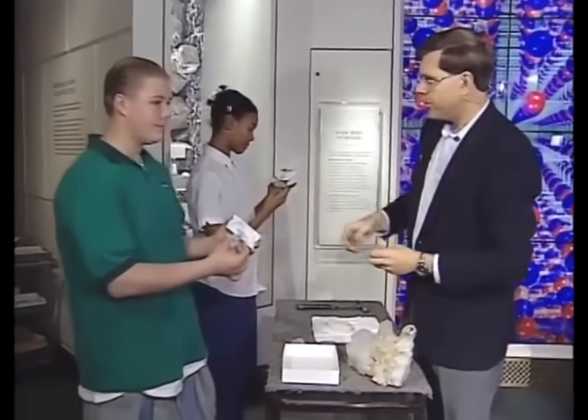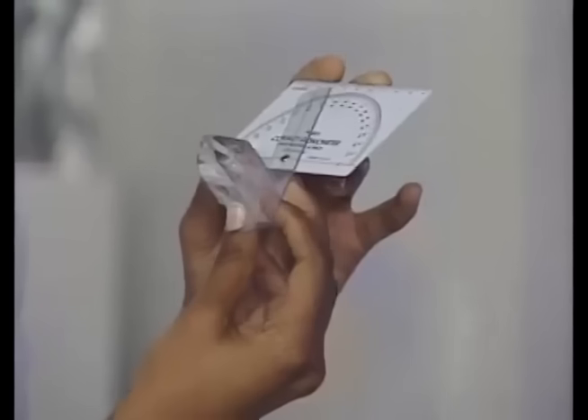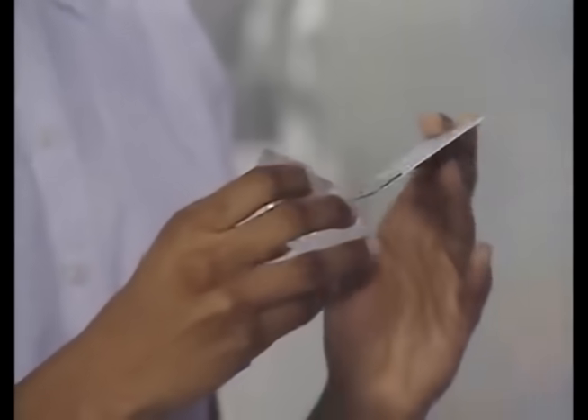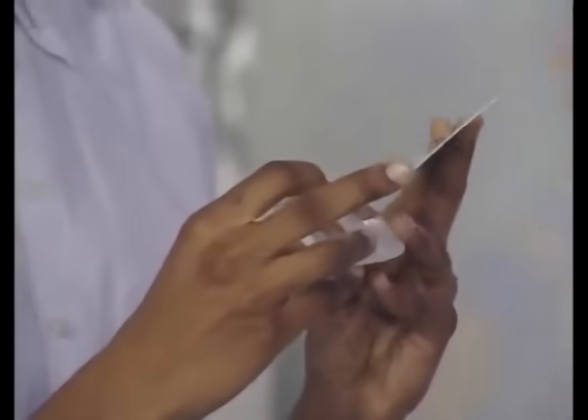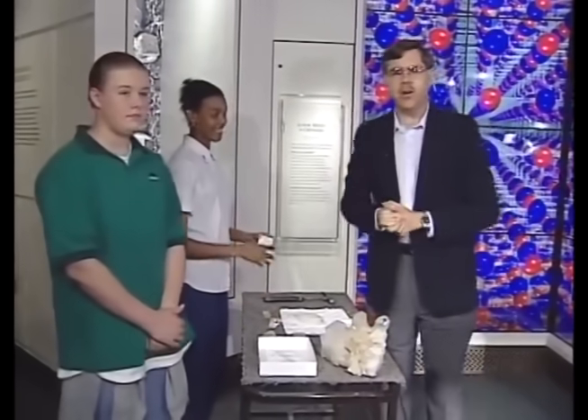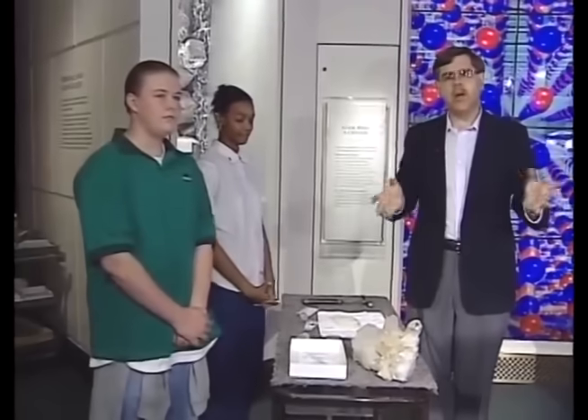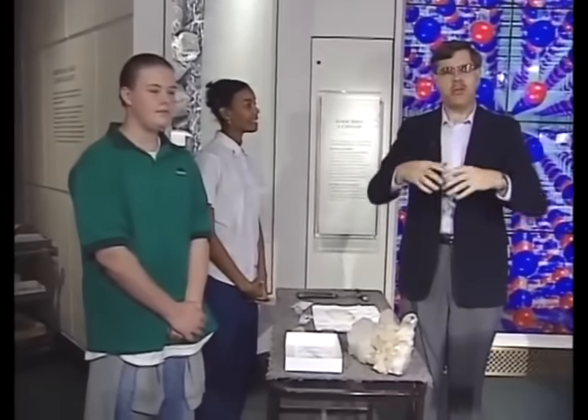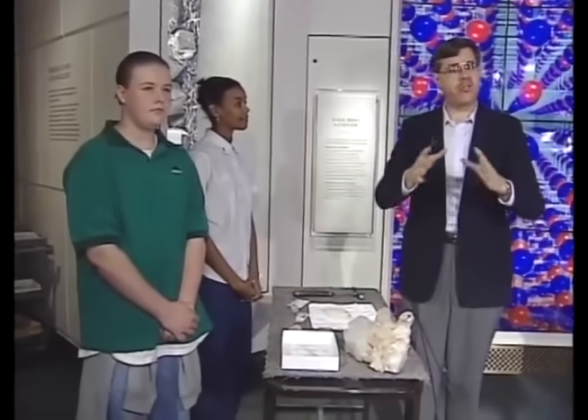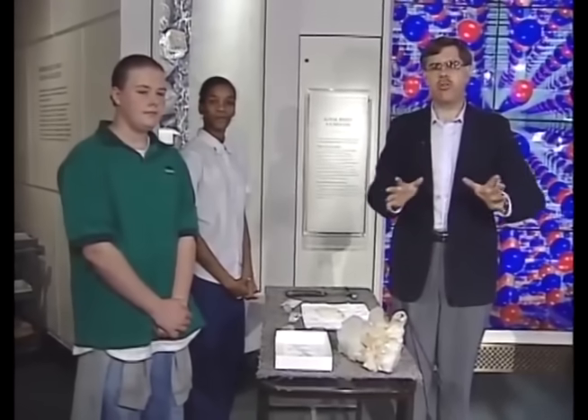If we measure, okay, Daryl gets 120 degrees. Well, that's pretty good so far. Kristen, what do you get? 120 degrees. So try this one, see if that one works. Okay, this is certainly an experiment you could try at home. And 120. So what Steno found, and what Daryl and Kristen found here, is that regardless of which quartz crystal you take, no matter where it came from, we always get the same angle. This implied there's something about the internal structure of quartz that's very orderly, very regular, and it's happening the same way for all of the quartz crystals.